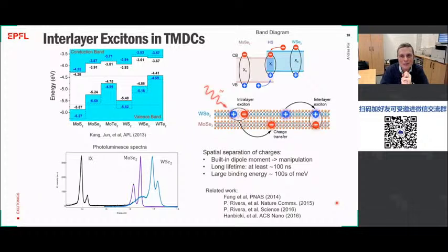And what is also interesting is that since you always have positive charge in one layer and negative in the other, these excitons will also have a dipole electric moment. So you will be able to manipulate them using electric fields and voltages. And the creation of these excitons is very easy to observe using, for example, photoluminescence.